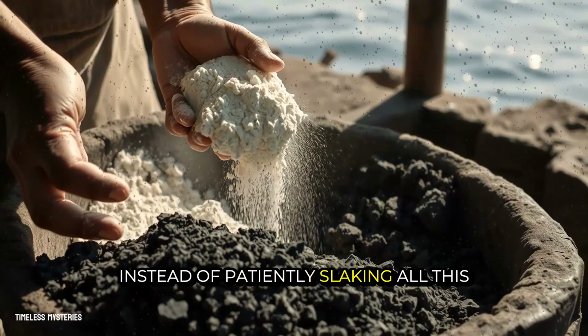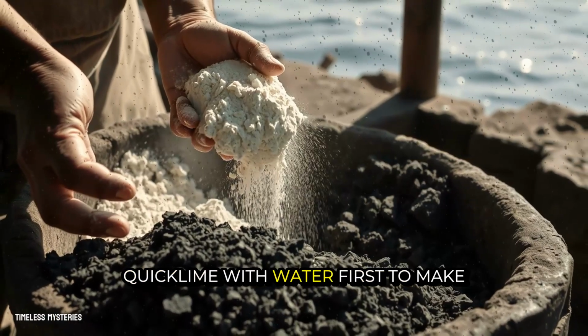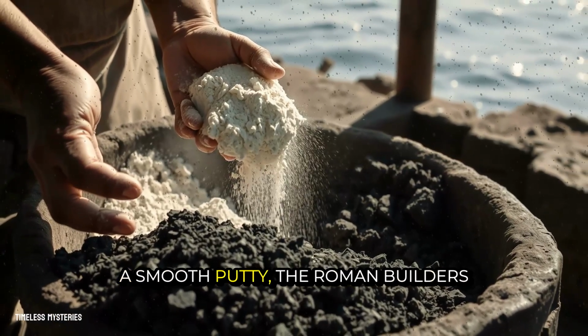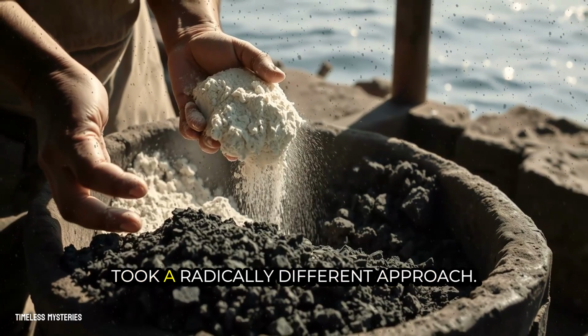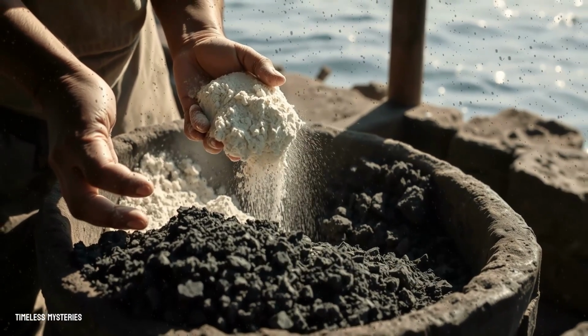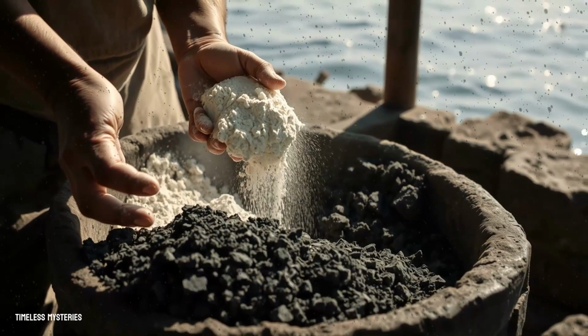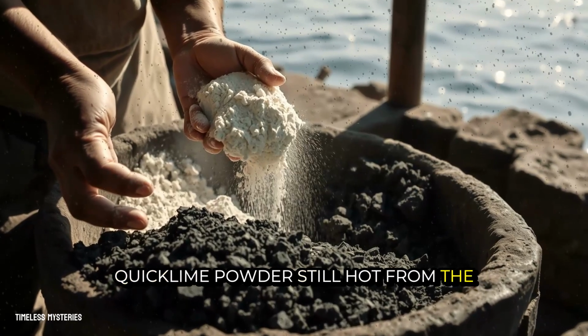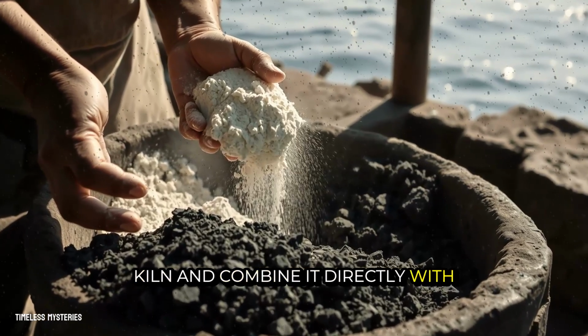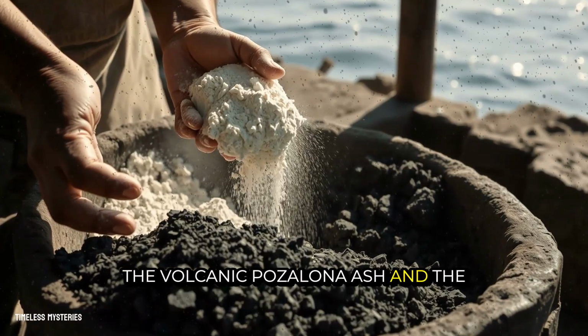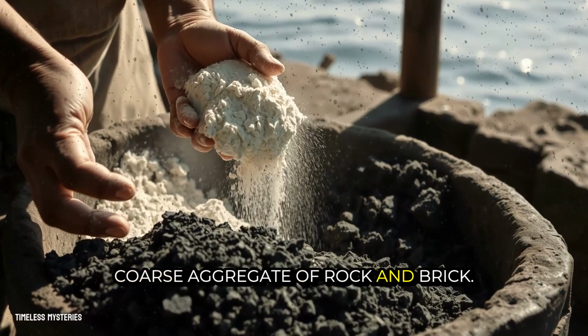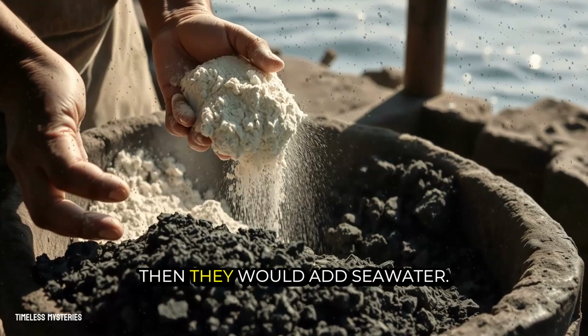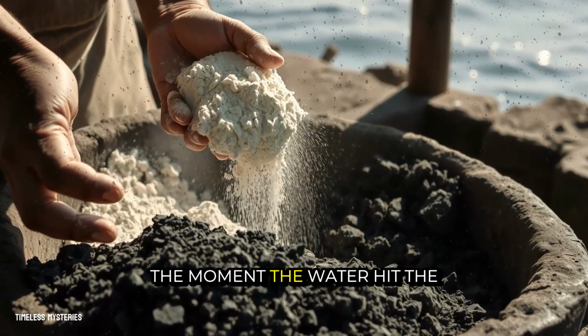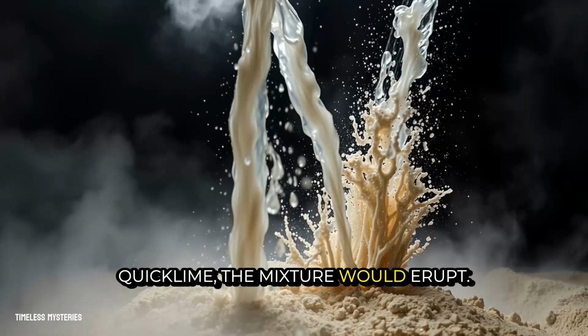Instead of patiently slaking all this quicklime with water first to make a smooth putty, the Roman builders took a radically different approach. They would take the dry, caustic quicklime powder, still hot from the kiln, and combine it directly with the volcanic pozzolana ash and the coarse aggregate of rock and brick. Then they would add seawater. The moment the water hit the quicklime, the mixture would erupt.